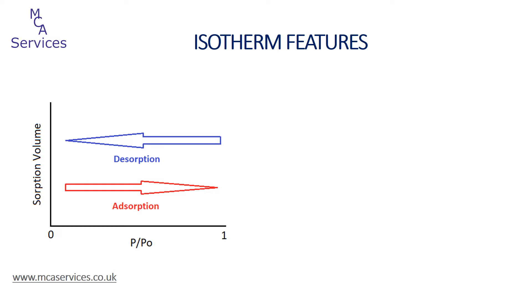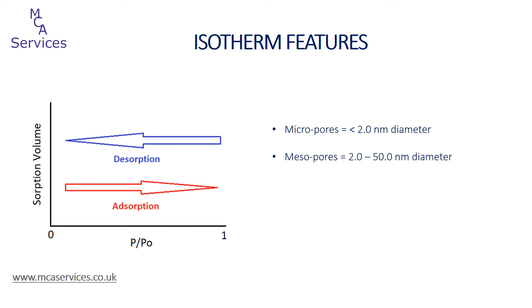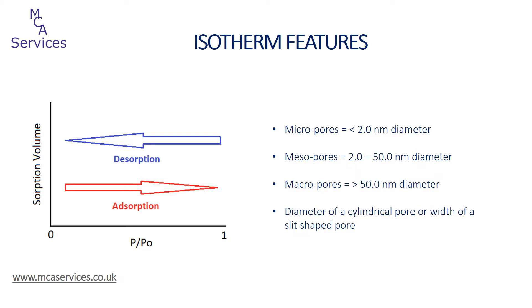When present in the sample, different characteristics of porosity present particular isotherm features. These profiles largely revolve around pore sizes according to the IUPAC classification: micropores which are less than two nanometers in diameter, mesopores between two and 50 nanometers diameter, and macropores which are larger than 50 nanometers. These dimensions refer to either the diameter of a cylindrical pore or the width of a slit-shaped pore, typically that of a carbon material.